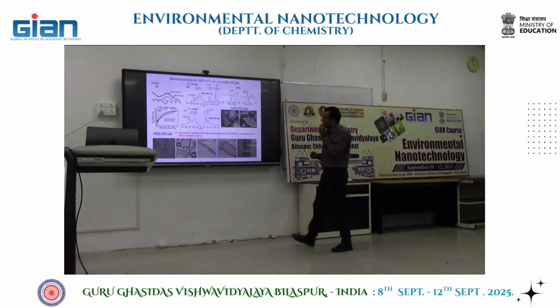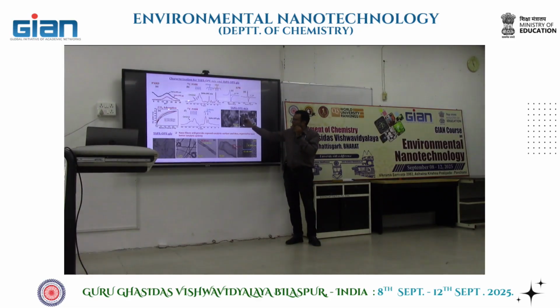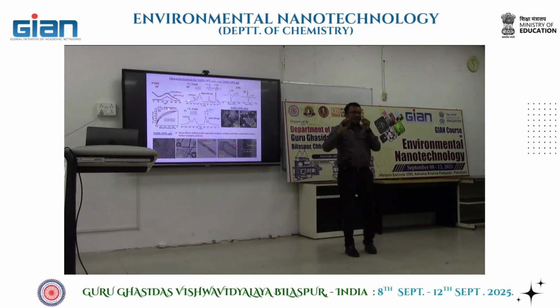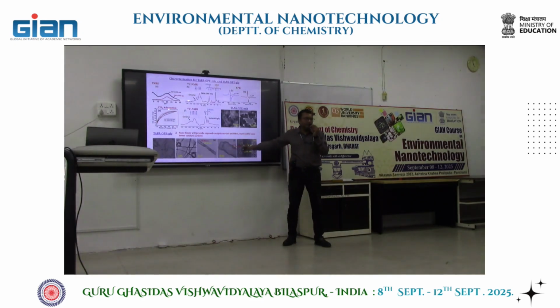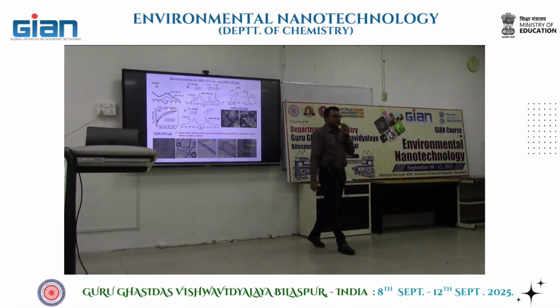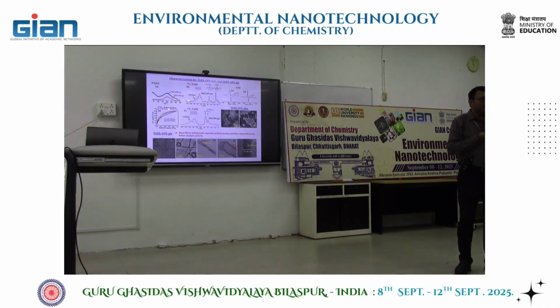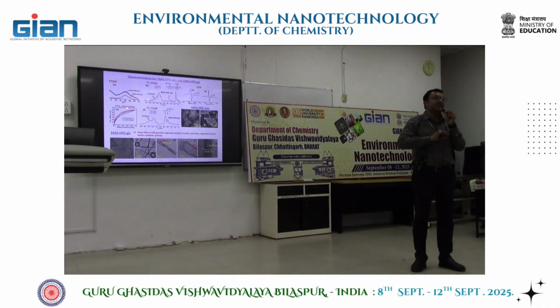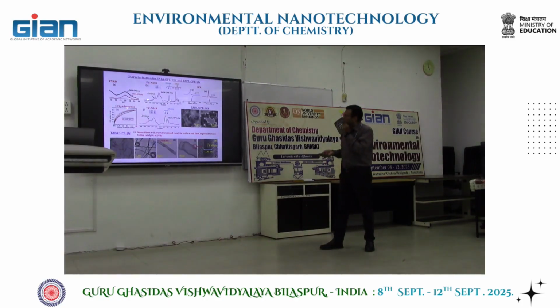The only important point is that if you have a mixed side chain, that ends up with an agglomerated or globular morphology, but the one having glycol chains on both sides resulted in a very nice fiber kind of morphology. And you have been continuously hearing since morning that if you have a narrow wire kind of morphology, which can provide high surface area, that can enhance the property. So just a small change resulted in a different morphology.